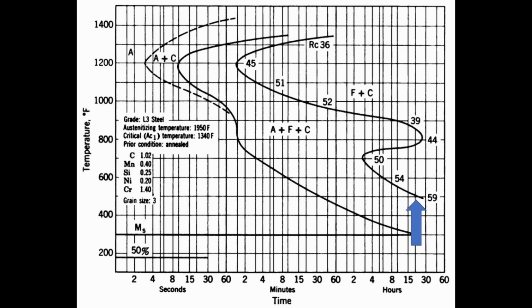The hardness was also slightly increased. Now this L3 is 59 Rockwell after being held at 500 degrees, where with the 52100 from 1550 was about 58 Rockwell. So there was a small increase in hardness for the same austempering temperature because of the higher carbon and alloy in solution.